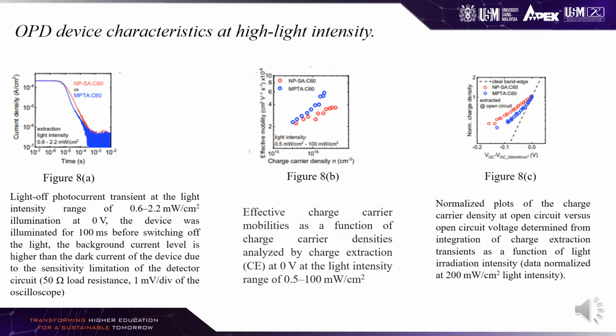This diagram shows OPD device characteristics at high light intensity. Figure 8a shows light-off photocurrent transients at the light intensity range of 0.6 to 2.2 milliwatt per centimeter squared, illumination at 0 volt. The device was illuminated for 100 milliseconds before switching off the light. The background current level is higher than the dark current of the device due to the sensitivity limitation of the detector circuit.